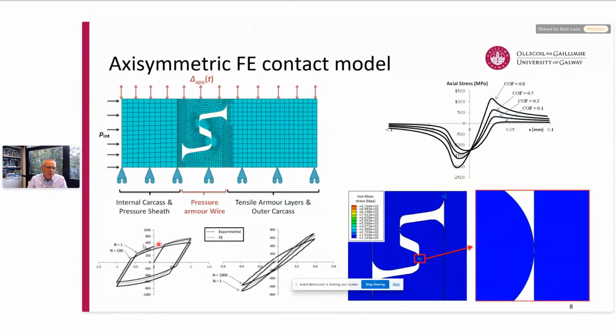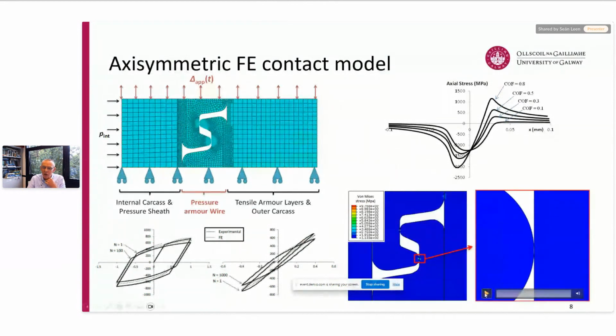In the bottom left, you can see we've actually modeled plasticity in this, and this is a comparison between our plasticity experimental strain hysteresis loops as measured and the finite element representation of those. And you can see that there's a cyclic softening behavior in the material, so that's represented in the model as well. And in the bottom right, you can see the images of the... how can I get out of this thing here? So there's a little animation there which shows the kind of cyclic behavior that represents the fretting behavior in the nub groove contact region of the model.